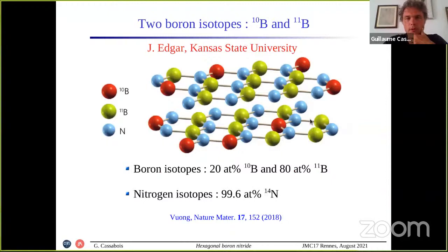So we performed studies by changing the boron isotopes. We were lucky to have samples from Jim Edgar from Kansas State University, who provided isotopically purified samples. The usual mixture is 20% boron-10, 80% boron-11. Nitrogen is almost pure naturally, but Jim Edgar managed to fabricate samples that are isotopically purified.